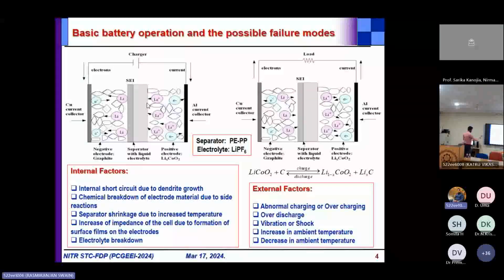Now here I have listed down some of the internal and external factors of degradation. The first point is internal short circuit due to dendrite growth. Internal short circuit will happen if there is formation of dendrite. What is a dendrite? If there is breakdown of lithium active material and deposition of metallic lithium on the anode surface, that gradually forms a crystalline structure, and gradually it will try to penetrate the separator. Due to that, there will be a short circuit between the cathode and the anode, which may eventually result in a catastrophe, and the battery may even catch fire.